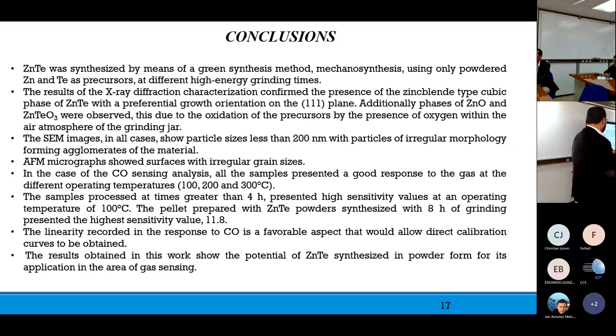These species result from the oxidation of the precursors by the presence of oxygen within the air atmosphere of the grinding jar. The SEM images in all the cases show particle sizes less than 200 nanometers, with particles of irregular morphology forming agglomerates of the material. And the AFM micrograph showed surfaces with irregular grain size.